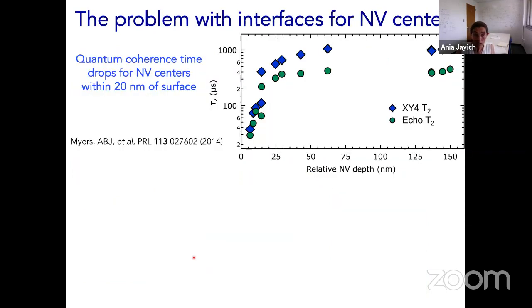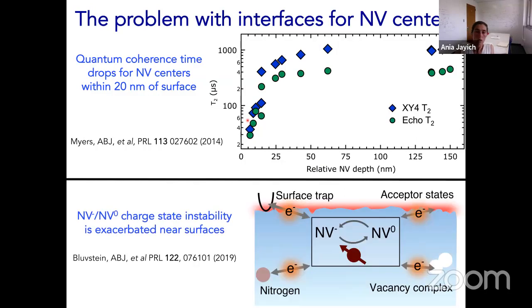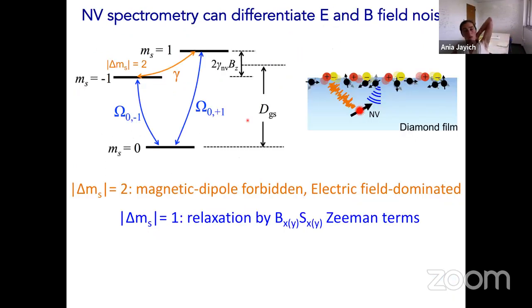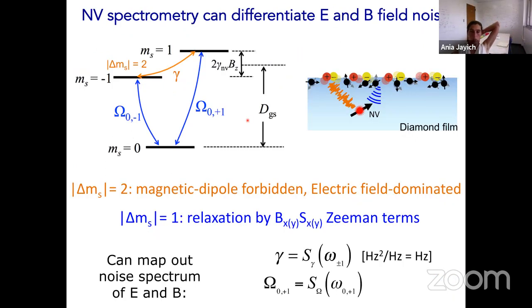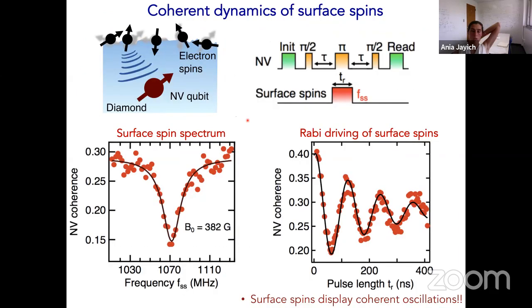For NV centers in particular, we've seen that the quantum coherence time of an NV center drops dramatically once you bring the NV center within about 20-30 nanometers of the surface. So this just plots T2 as a function of depth. Again, things are sort of bulk around 20-30 nanometers, but drop when they get near the surface. In addition to quantum coherence dropping, charge state stability of these defect centers also tends to get worse near surfaces. It's just yet another problem with interfaces and surfaces. I think I will skip these two slides because I want to get to an interesting point.